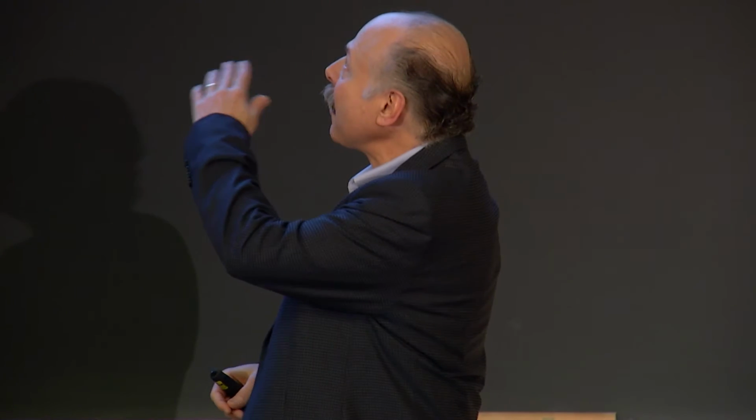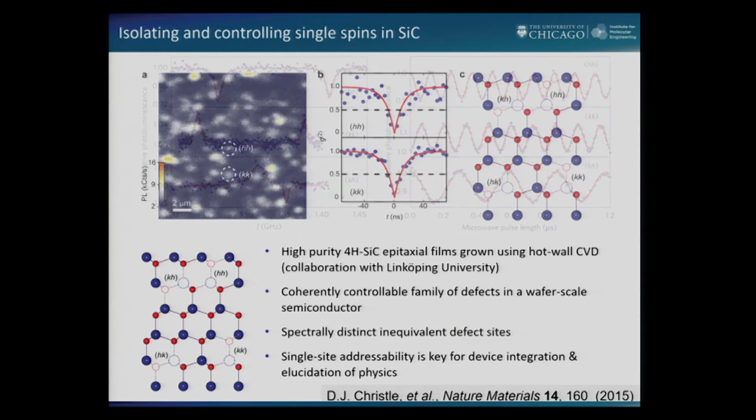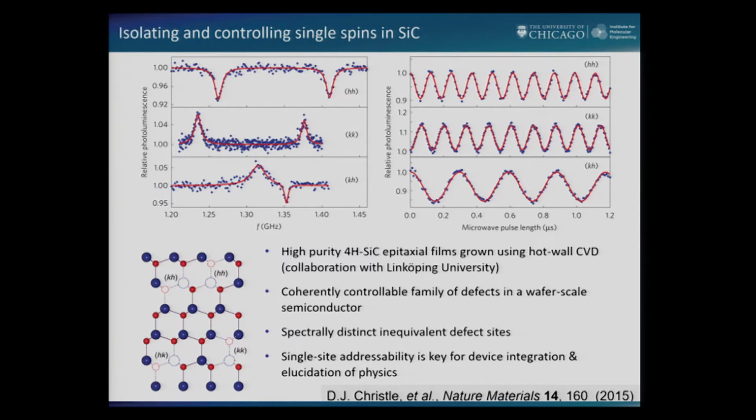We'll move on. So if you take a wafer of silicon carbide and look for individual spin states, sure enough, they're there. They're actually in the near infrared, right in the telecom region, which is pretty interesting, right where the theory predicted, which is quite striking to me. And because this particular polytype I'm showing you has a particular lattice design, there are 3 distinguishable spin states in different crystal locations, each with its own Rabi frequency, each with a spin pointing in a particular direction.